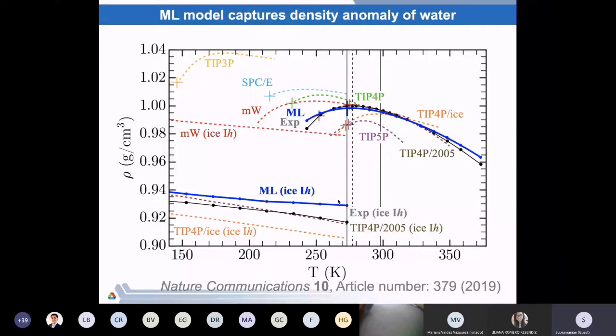And that is basically because of the data-driven approach. We took an elaborate training data set, and by following this procedure, we were able to come up with this new model. So this is a huge improvement over the state of the art. And this is something that one can extend to other types of systems as well. But water is just an example where people have been trying for decades to capture these simple properties. Something as simple as the location of the correct melting point and the temperature of maximum density was often difficult for people to capture. And so this use of machine learning has shown that one can come up with a better set of parameters that can capture all these features.